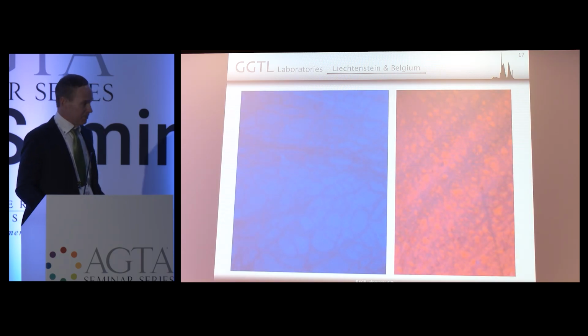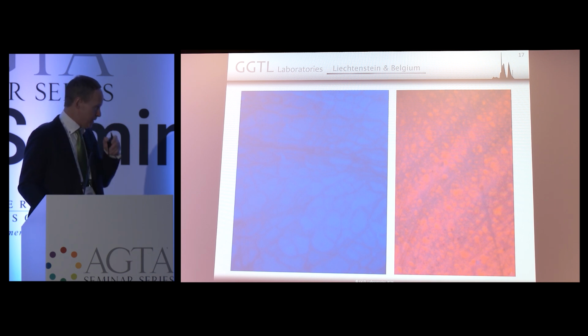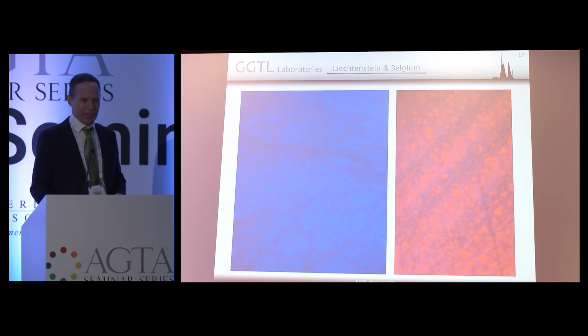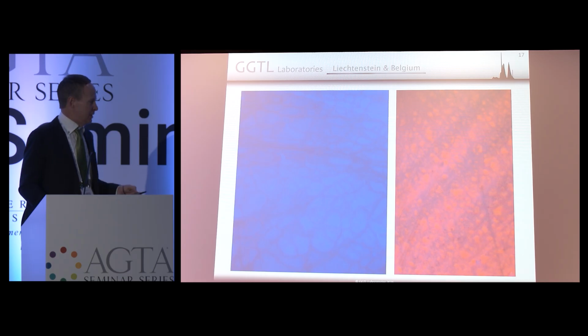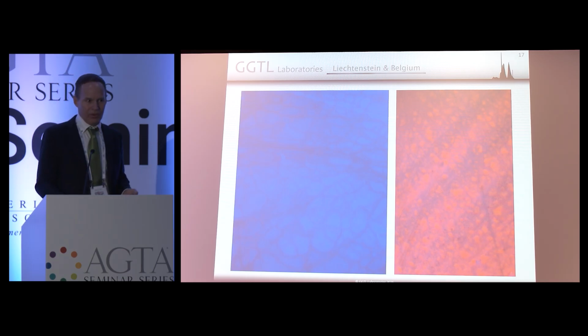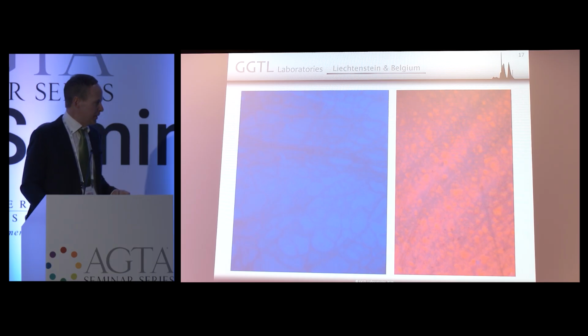Two more examples. On the left, a blue fluorescing one with dislocation network. On the right side, one with red fluorescence from the NV center. So those are also dislocation networks. They can occur in practically any color, these images. They're all deep UV excited as well. So here again, deep UV does the best job because type 2A diamond is transparent all the way to 225 nanometers.